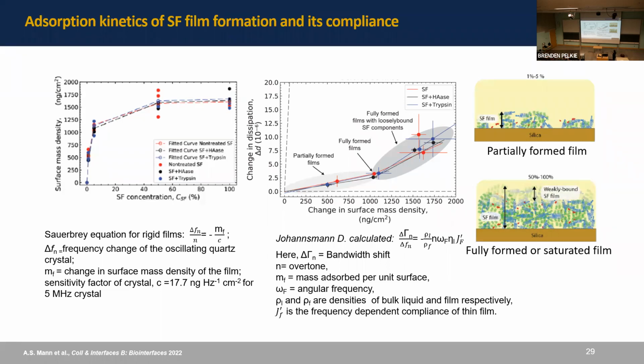And then as we increase the bulk concentration from which the synovial fluid film is formed, there is now a loosely or weakly bound synovial fluid film that can be easily washed by flowing PBS during the washing step. And we can also estimate the changes in dissipation from the QCMD experiments, and we can measure the JF prime, which is the frequency dependent compliance of the thin film.